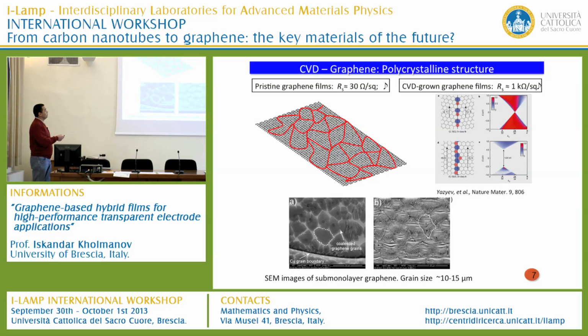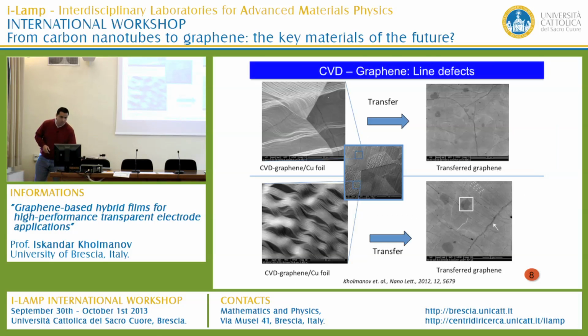First of all, CVD grown graphene is polycrystalline. The graphene domains have an average size of about 10-15 micrometers. If you grow and obtain continuous CVD grown graphene, the graphene domains form grain boundaries between each other. It was theoretically demonstrated that, depending on the atomic structure, these grain boundaries can be transparent for charge transfer, while they may also create a barrier for charge transfer. These grain boundaries are today unavoidable, and we need to address them when fabricating CVD grown graphene for TCF applications.